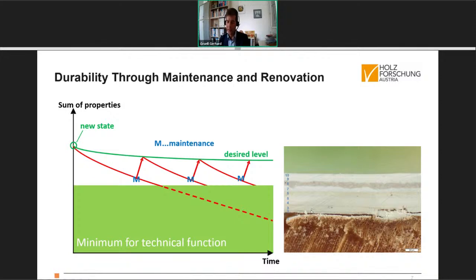This image here on the right side is an example of a sample from a historic wooden window, where you can see a layup of different coatings, which are basically maintenance work done over the last 40-50 years or so. And you see that we found in total 10 different coating layers on top of this historic wooden window. And this is all maintenance done in a stage when the old coating was still in good condition, because otherwise we would have seen that on the window, that the maintenance work didn't really make success. In this case, it worked 10 times, and this layup of maintenance coatings is shown here very impressively.